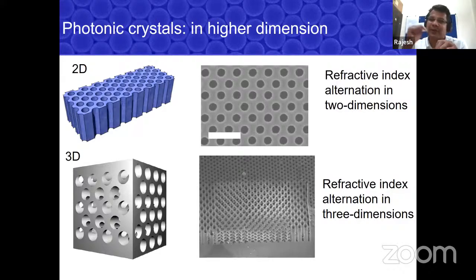You take a material, and you make a periodic array of holes with a periodicity of the order of 300 nanometers. So this is a real sample picture that people made in the laboratory in a silicon wafer. You can see that there is a nicely periodically arranged refractive index variation. All these black regions are air, the material is removed, and the gray regions are the silicon. So when the light propagates from the left side to the right side, it does see this variation in the refractive index. And when the light goes from, let's say, top to down, you still see a variation in the refractive index contrast. And that is why it's called a two-dimensional photonic crystal. That means if I launch light from this direction and this direction, I should get a band gap for light.